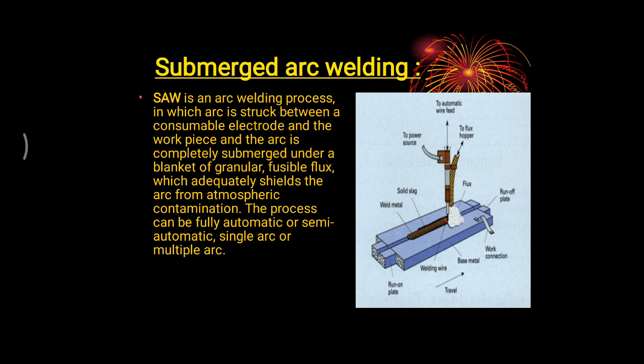Submerged arc welding has a deposition rate of 20 kg per hour and a welding velocity of 5 meters per minute. The current is 200 to 2000 ampere, and the thickness of the plate can be minimum 10 mm, maximum up to 50 mm.